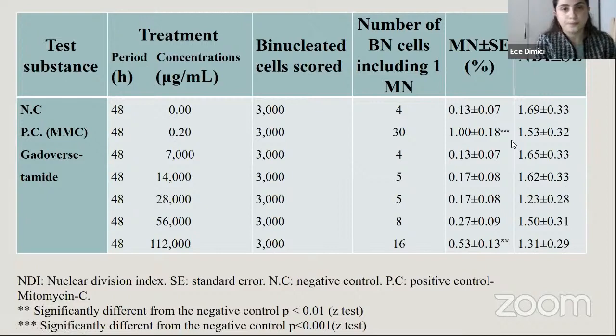And if you look at the table, here is the treatment. This is the period, and these are the concentrations. Negative control, positive control, mitomycin C, and gadoversetamide treatments. Here, binucleated cell scores, all of them are 3000, and the number of binucleated cells including 1 micronucleus for all the treatments, micronucleus and nuclear division index. If you look at the gadoversetamide treatments, in the micronucleus section, we can see an increase according to dose, except the lowest concentration, compared to negative control. And only the highest concentration has a statistically significant difference.